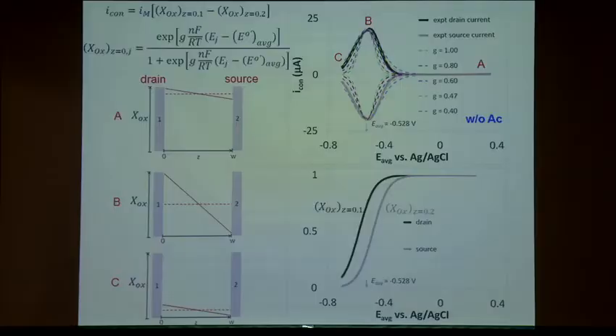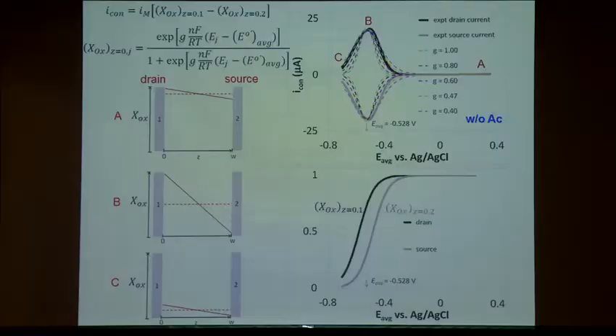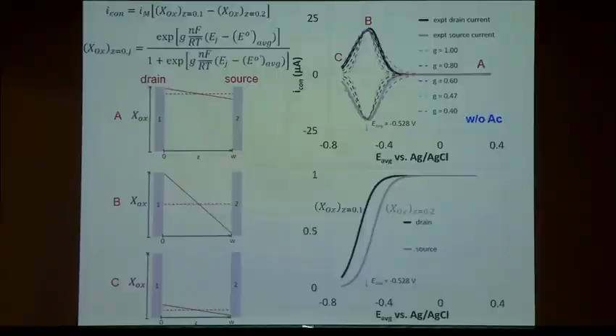And the key thing is this here. When both electrodes are very positive in potential, I can't get any electrons into the biofilm. Even though there's a bias between them, both electrodes are too positive, so I can't reduce any of these charge transfer mediators. If I can't reduce them, there's no conductivity. And that's exhibited down here in this region. At the other extreme, if both electrodes are very negative in potential versus the formal potential of the mediators, then all the mediators are going to be reduced. There's no holes, no oxidized mediators in the biofilm to accept an electron to get a hopping event to happen to get conductivity. So the model predicts all the way out over here we would have zero conductivity.